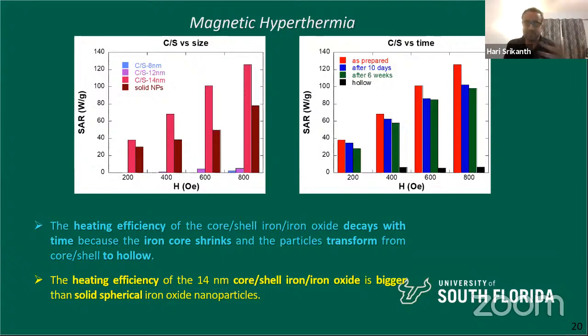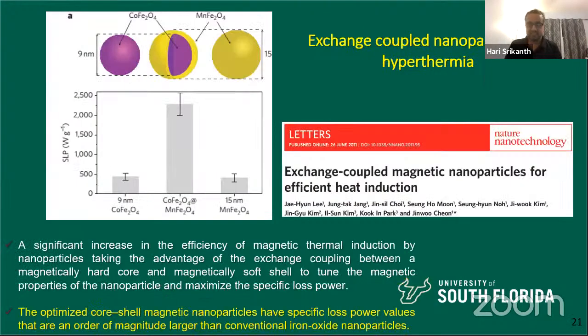Now, if you think about it, the best way to do that is to have all oxide core shell. Namely, the inside core is also oxide, and the shell is oxide, biocompatible iron oxide, of course. And then, of course, you don't have this Kirkendall effect. So we were thinking about it, and there was a group in Korea that actually made this before us. But they used cobalt ferrite and manganese ferrite. They actually showed that this is exchange coupled. Because cobalt ferrite is a ferromagnet, manganese ferrite is an antiferromagnet. So it's like a nano spin valve, okay? It's an exchange bias antiferromagnet system core shell. They actually showed that this exchange bias can be seen.